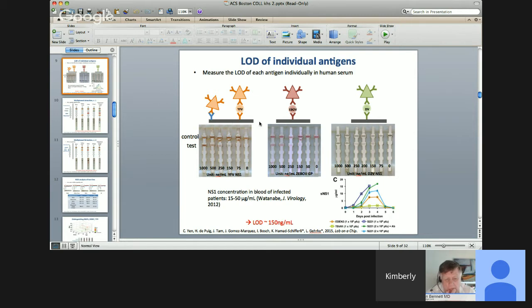So we do this for yellow fever. We do it for Ebola. You can see that now everything is red because it has the red particles, and we do it again for dengue, and this time it's green because we use green particles. And the limit of detection for all these tests is in the order of 150 nanograms per mL.